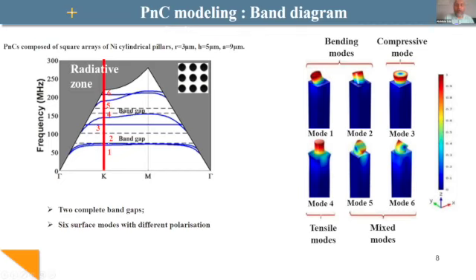And the modes are labeled from 1 to 6. If we see the shape deformation of these modes, we can see that mode 1 is a bending mode, mode 3 a compressive mode, and the others tensile and some mixed modes. But for all these modes, the deformation is localized in the pillars.